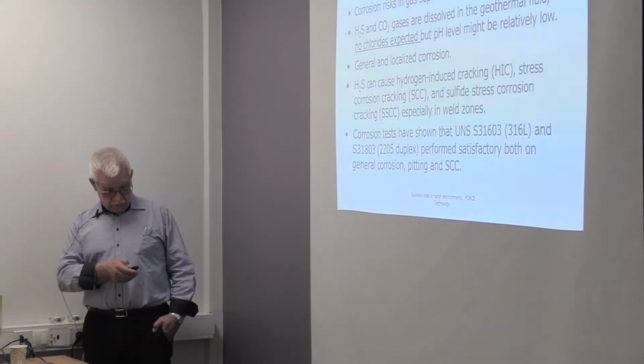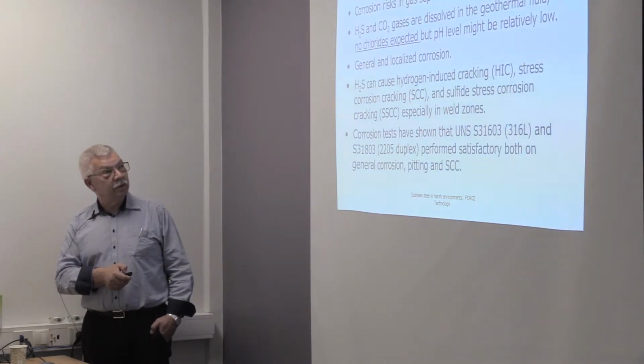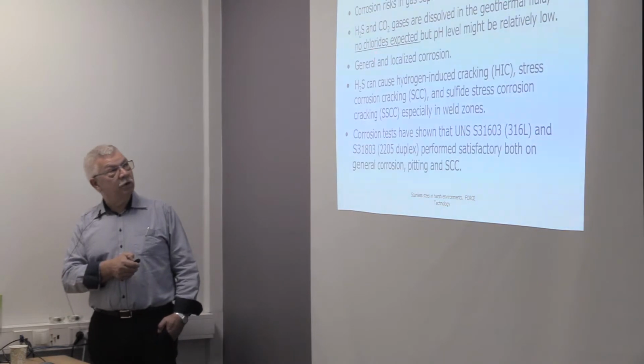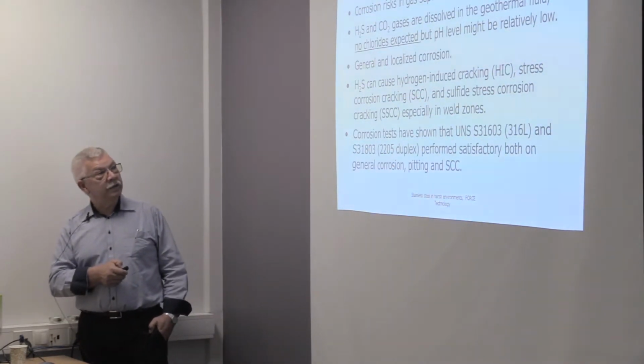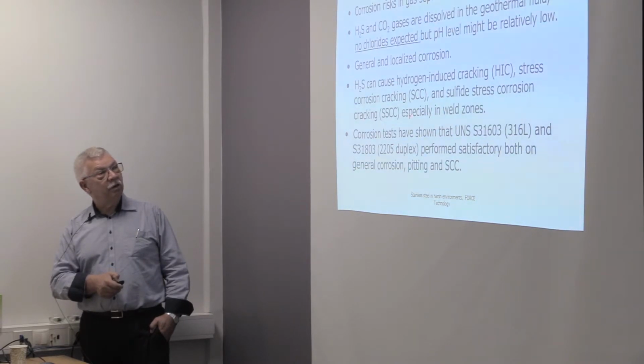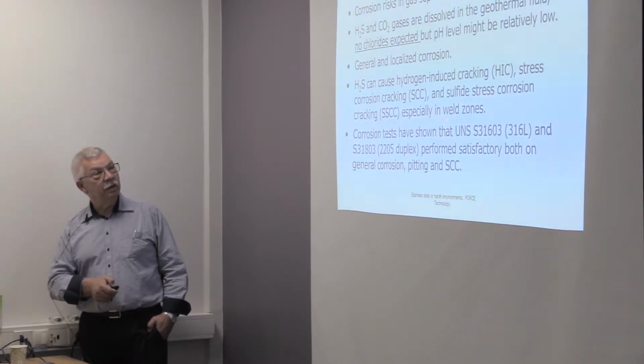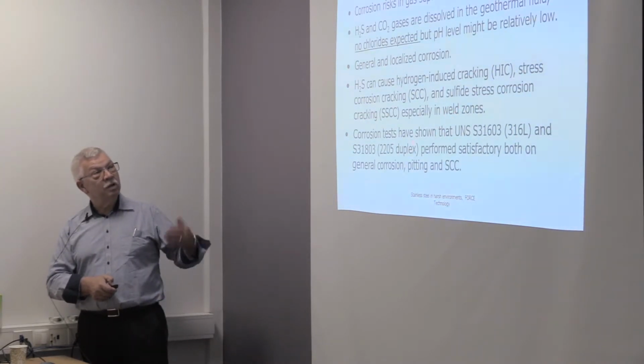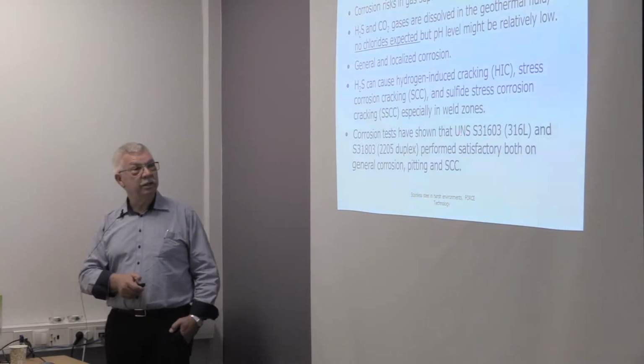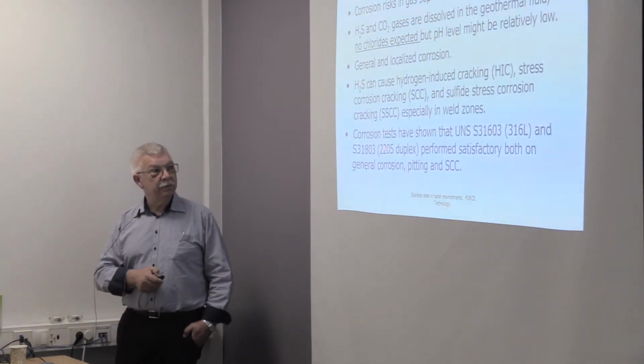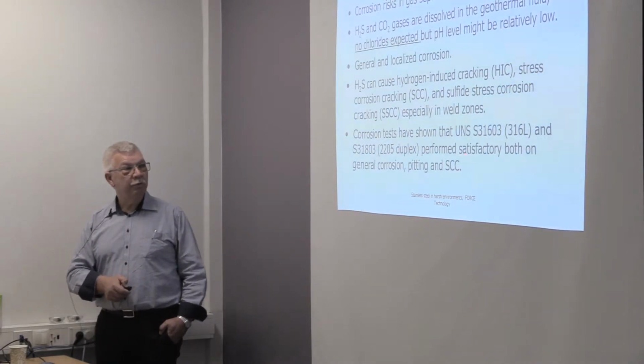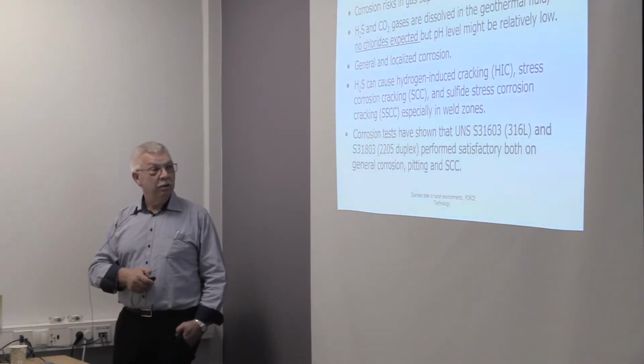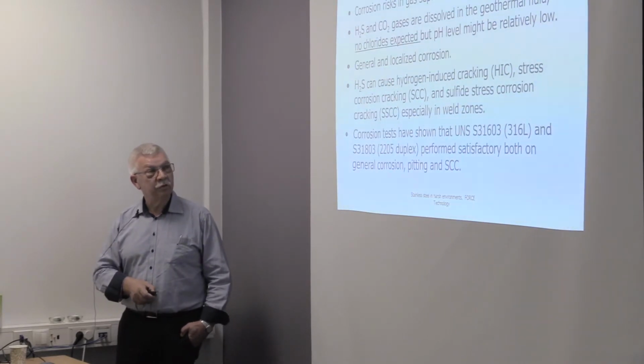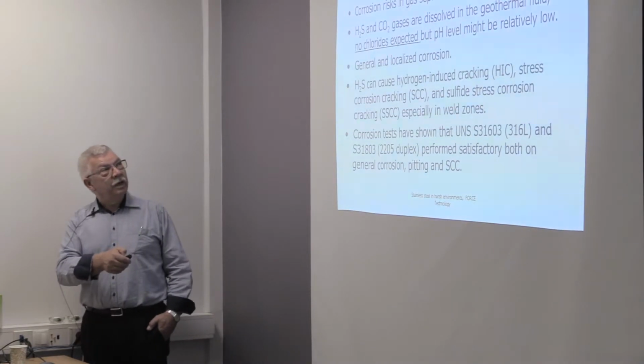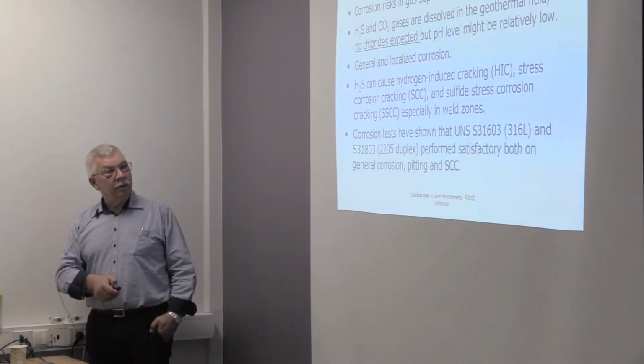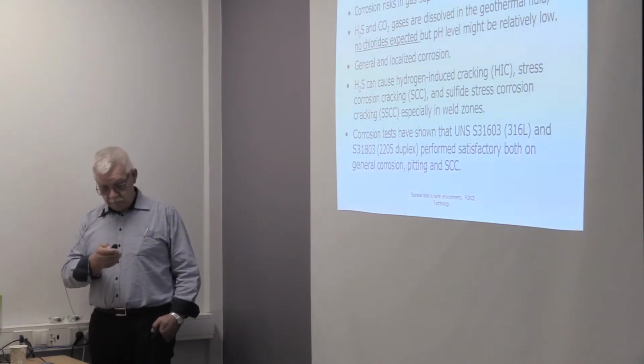We have to look into stress corrosion cracking, not from the chlorides, but from the H2S. There would be a risk of corrosion in the weld zones. But the test done for this particular system was that the 316 stainless steel and the duplex 2205 would perform satisfactorily. No general corrosion, no pitting, no stress corrosion cracking. So due to the level of chlorides, an ordinary stainless steel would apply for this one.